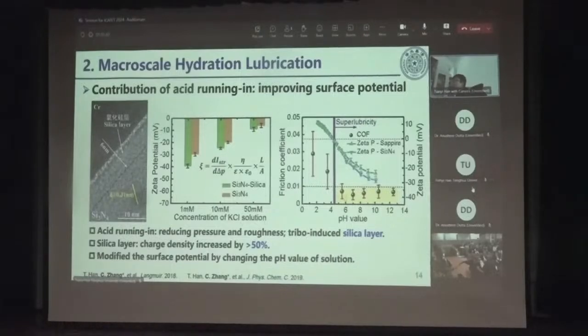And then we can modify the surface potential by changing the pH value of the solution. We see as the pH value larger than 5, in this region, the surfaces are negatively charged, and we can obtain a super low friction coefficient. But if the pH value decreased less than 4, the surfaces became positively charged, and then the friction coefficient increased.